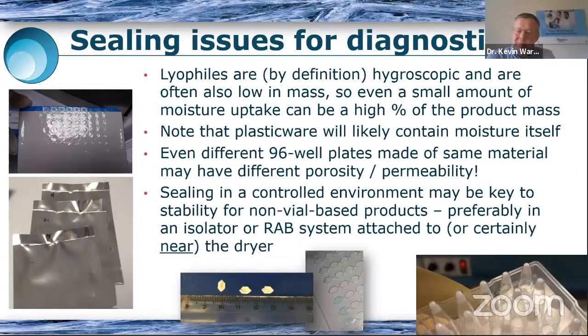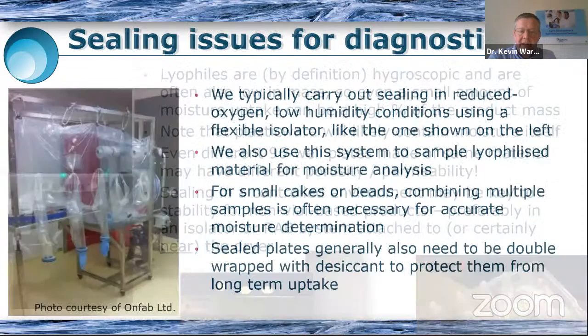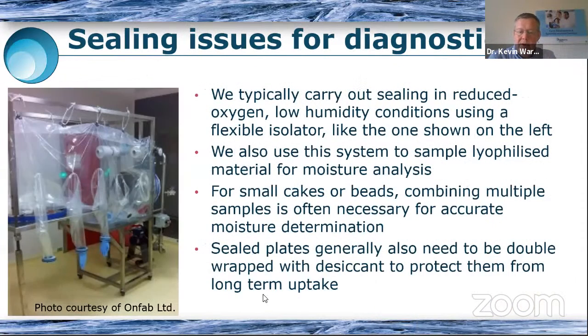And what we found was that plates that are even made from the same polymer, like polypropylene, polyethylene, they can have different porosities from different manufacturers. And so this became a problem that we actually didn't expect. So sealing is really important to optimize, and we typically use a nitrogen dry box, as you can see here, a nitrogen tent, where we can limit the humidity and limit the amount of oxygen while we carry out the heat sealing and we carry out the secondary packaging.